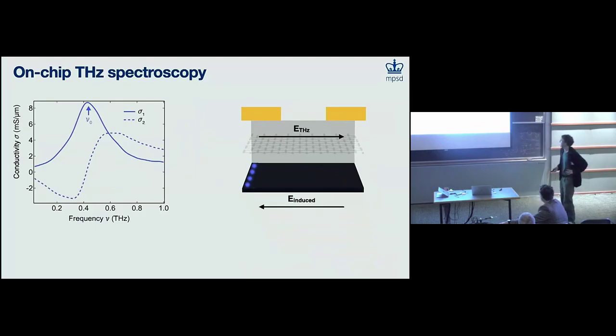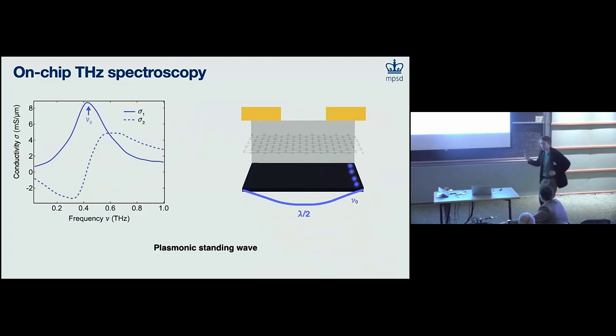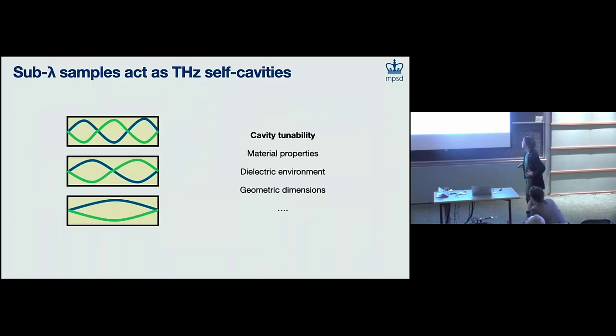This creates an electric field in the opposite direction, which acts as a restoring force, and this triggers a plasma oscillation. And so this example I just showed, this would be the half wavelength plasmon standing wave. This is the lowest order mode that you can get. The takeaway message is that these tiny sub-wavelength samples naturally act as terahertz self-cavities. And so you're going to get polaritons bouncing off the walls if the sample's small enough, in different harmonics.